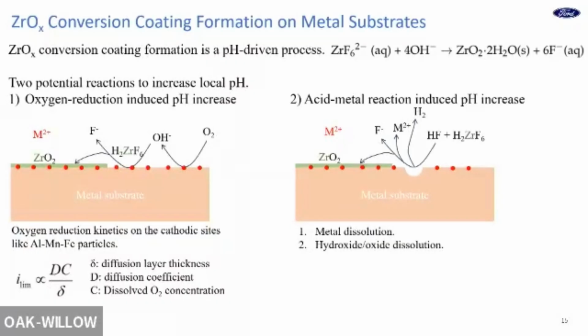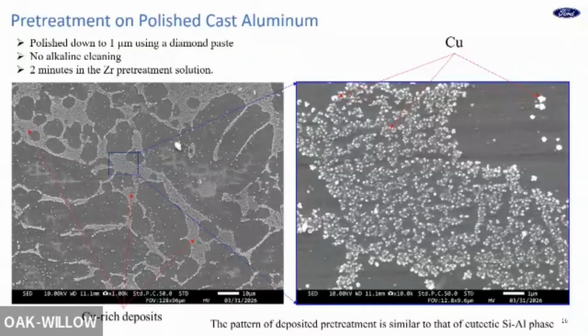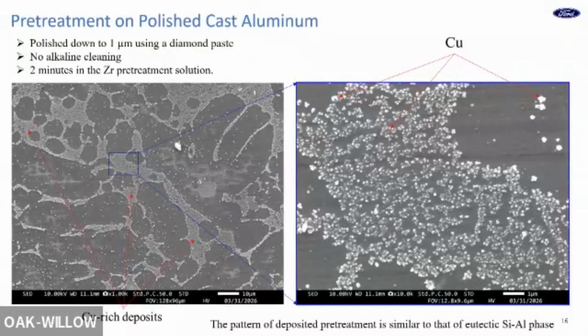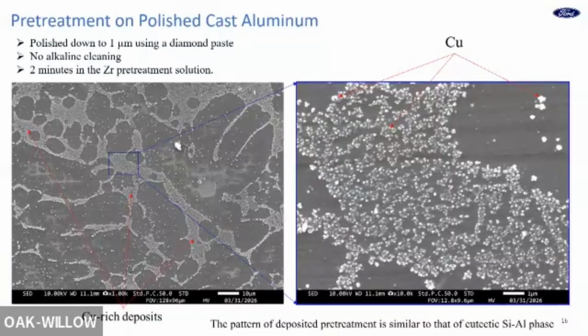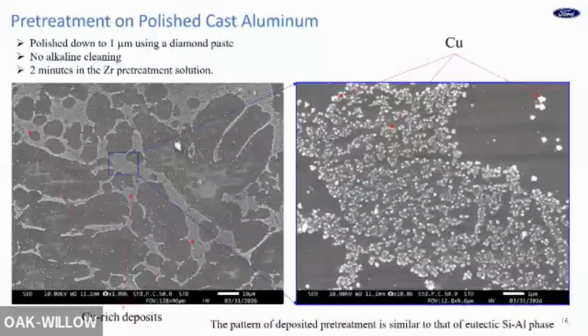To have a better understanding, we did a simple test. We skipped the alkaline cleaning pretreatment. We polished the sample so we can reveal the microstructure: the eutectic silicon and aluminum, this kind of layered structure, and also reveal the pure aluminum phase, and then dipped this in the pretreatment solution. If you look at the zirconium, these white precipitates on the surface have high copper and also zirconium, and this deposition pattern matches very well with the eutectic microstructure. If you zoom in on this local area, you do see this precipitate is like a layered structure. This layered structure can be silicon, it can be aluminum. In our understanding, copper can be reduced by aluminum, then form a copper layer, then promote the zirconium pretreatment.